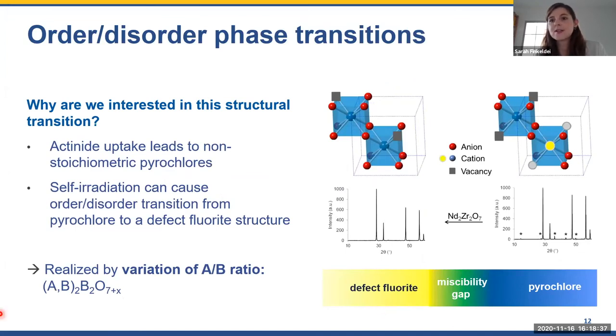So we are interested in this order-disorder transition from a pyrochlore to a defect fluorite because, as I said, whenever we have zirconate-based pyrochlores, this is basically the response of the material to radiation. And we are also interested in this order-disorder transition because whenever we load our waste form phase with an actinide, we are actually obtaining so-called non-stoichiometric pyrochlores, because we will have mixed occupancy at the A or at the B site. And the self-irradiation, once we upload a radionuclide and immobilize it in a pyrochlore structure, can cause this order-disorder transition. And what I've done is I realized this by variations just of the A to B ratio. So I replaced part of the A-side cation with a B-side cation to move from a pyrochlore to a defect fluorite structure.